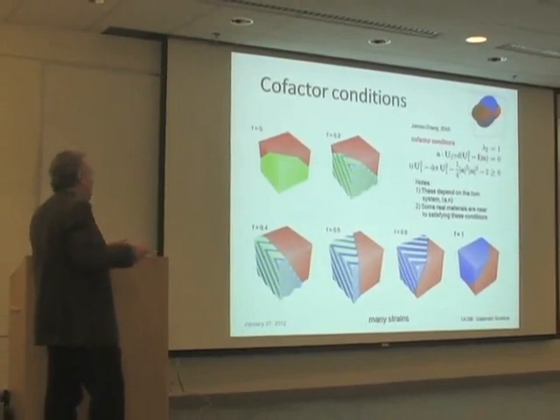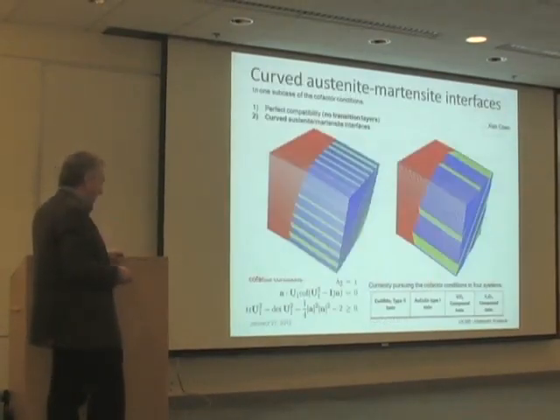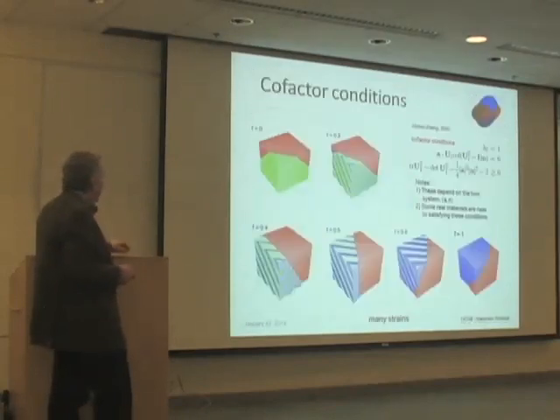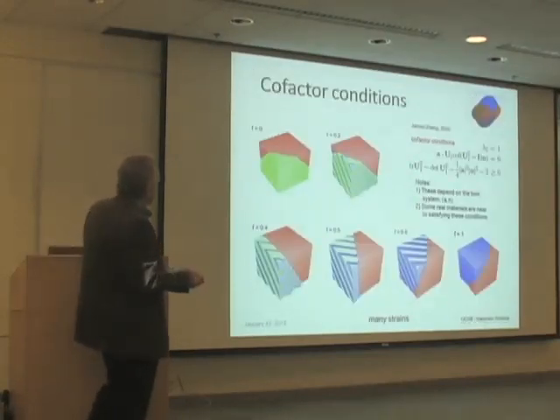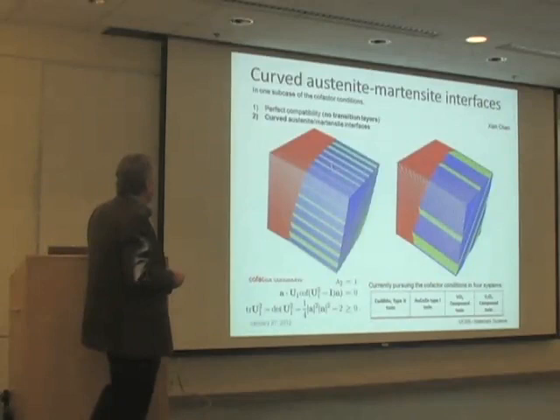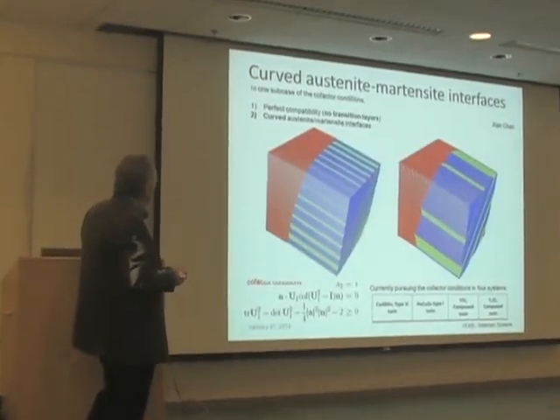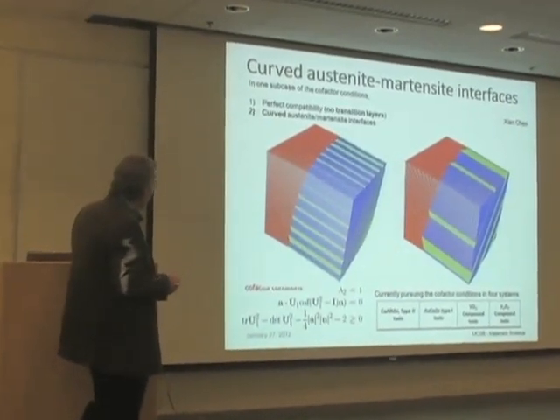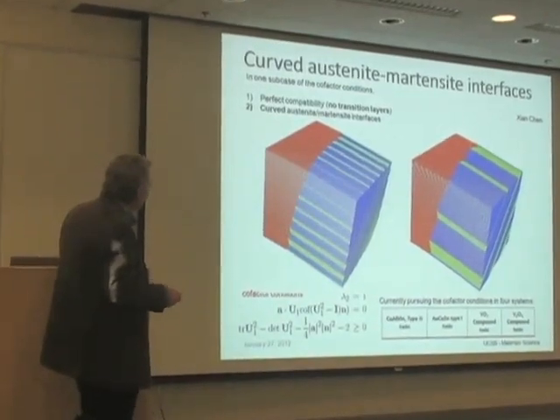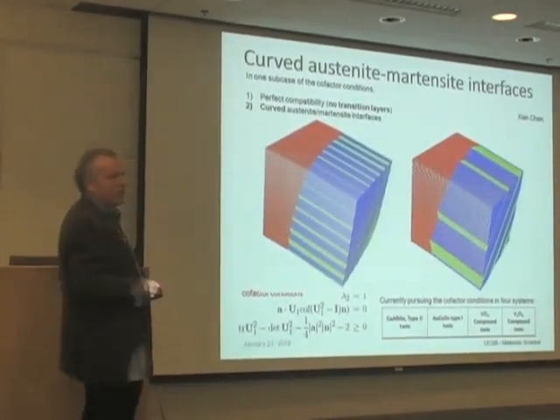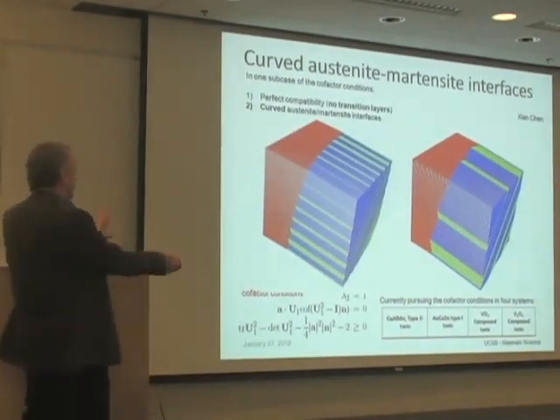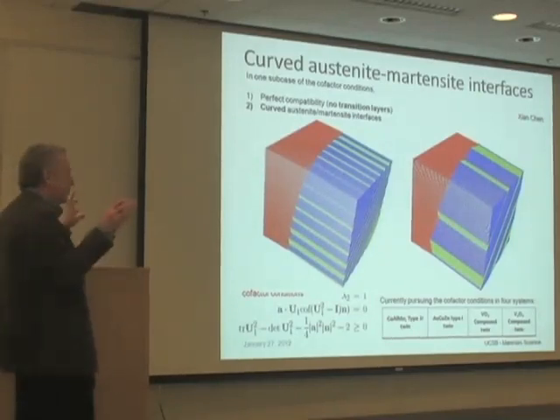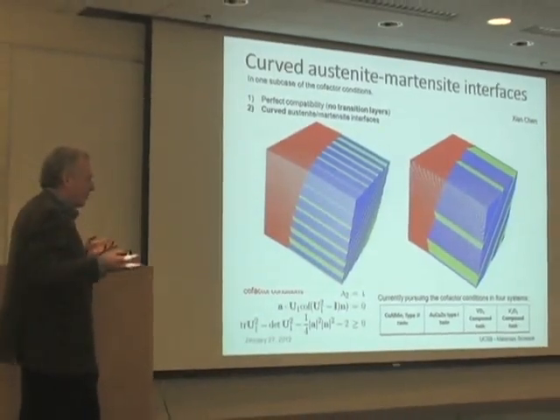So it's a really interesting condition. We noticed recently that in a special case of these conditions, which can be satisfied in real materials, not only do we have that, but we actually can have curved austenite martensite interfaces and no transition layer at all. So you can see everything's fitting together here. It's like a jigsaw puzzle where all the pieces change shape, but they all perfectly fit together without stress. It's kind of like that.